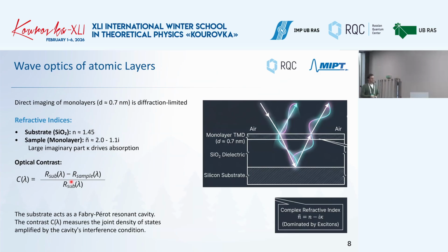Yeah. Just a few words about this complex refractive index. I will not talk about this anymore in the presentation, but I think it's important to stress that different layered materials, different van der Waals materials, they have different complex refractive index, and a lot of studies demonstrate there are different interesting properties like anisotropy and so on of the different orders. And basically people in MIPT, in the Center of 2D Materials and Photonics, where our lab is, they are studying these materials with ellipsometry, so they can directly evaluate N and K parameters, and they made lots of works demonstrating that indeed for some materials you have anisotropy, for some not, and in some cases they have really huge values for these parameters.